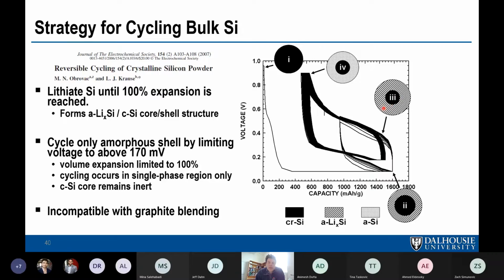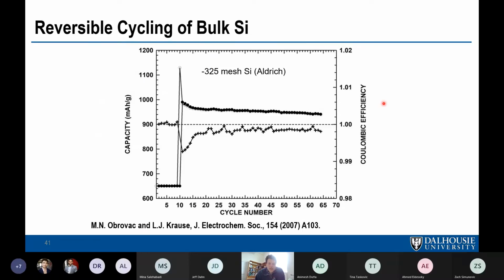And so then you cycle these tiny core shell particles, and they can cycle very well. You can think of this as, we saw that sputtered film on the copper substrate. Well, now we have a film on a solid core substrate. So it's kind of the same idea. And this is silicon directly from the bottle from Aldrich. These are the conditioning cycles over here, 10 of them. And then after that, the voltage is limited above 170 millivolts. So you're only cycling that outer shell of silicon. And you can get very good cycling even from pure silicon out of the bottle.